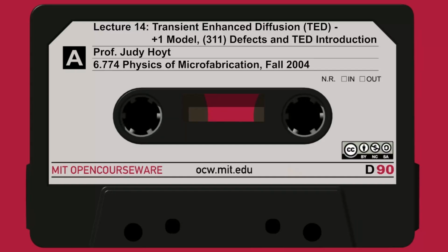This is very difficult to explain from a simple single diffusivity, which is exponentially activated with temperature. Because we know, if you look in your text for the intrinsic diffusion of boron, that at 1,000 degrees it's like 2 or 3 orders of magnitude higher. And yet here, this cannot be normal, regular intrinsic diffusion, because you're getting a lot less diffusion at 1,000.